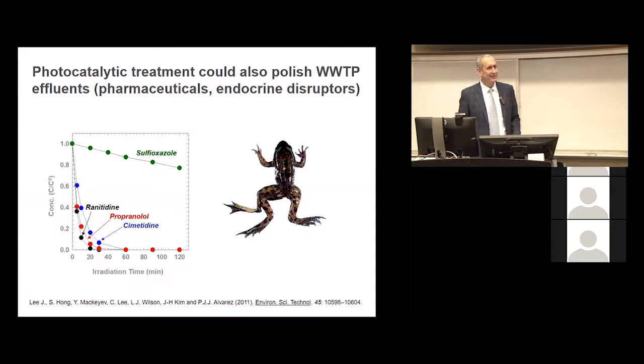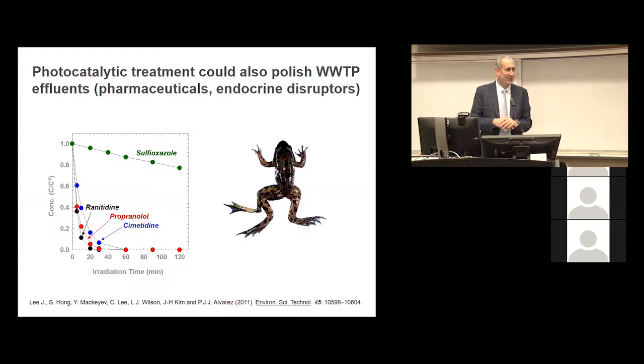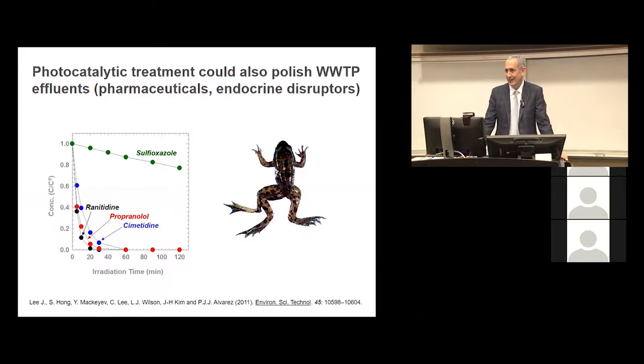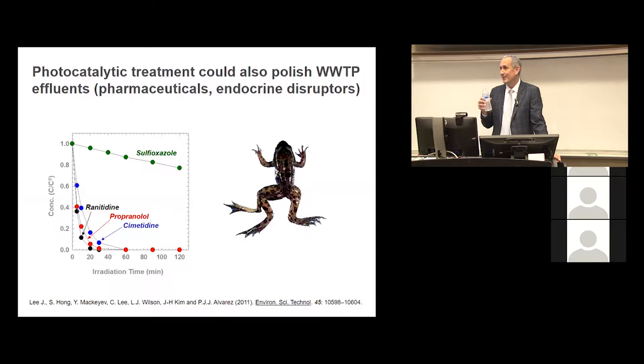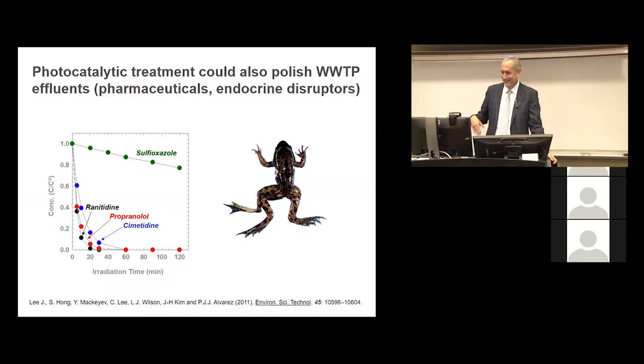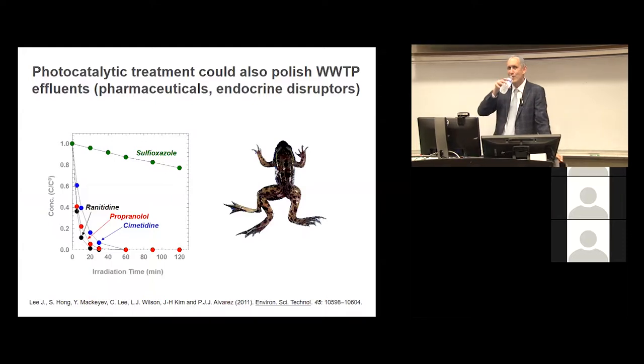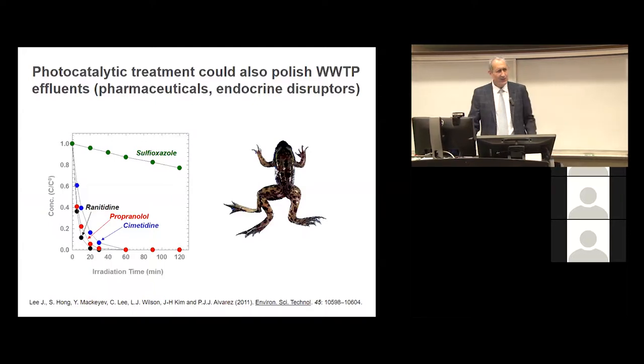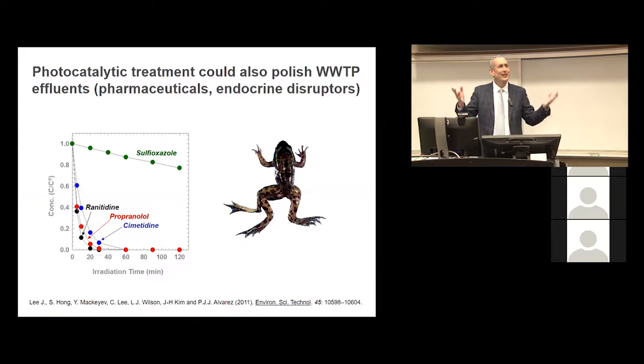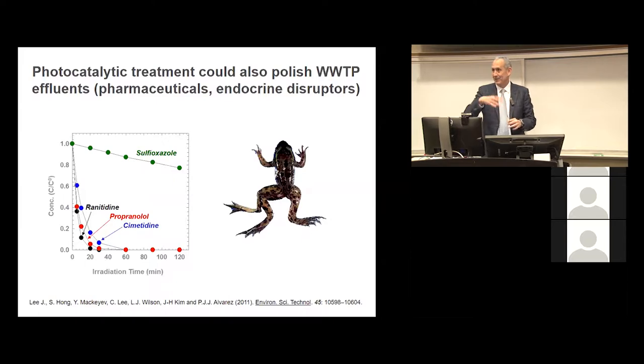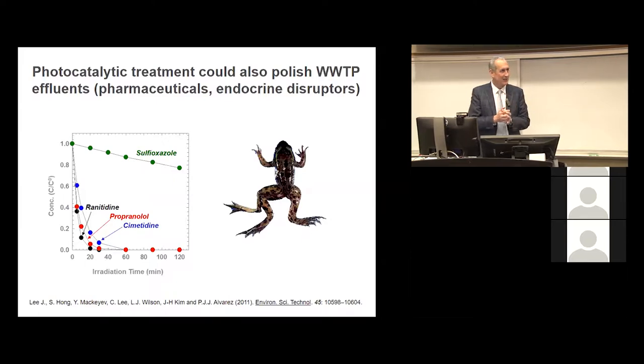So right here, this suggests one way we can start using nanotechnology without having to change system architecture too much. Most wastewater treatment plants in the US and Europe have UV disinfection. They have a UV chamber for disinfecting. You don't want to use chlorine because that generates disinfection byproducts that are nasty. So you can very easily retrofit this UV chamber and make it a fluidized bed reactor with these floating beads that are easier to retain for reuse, that are essentially coated with nanoparticles.